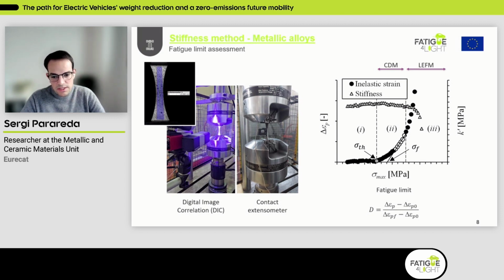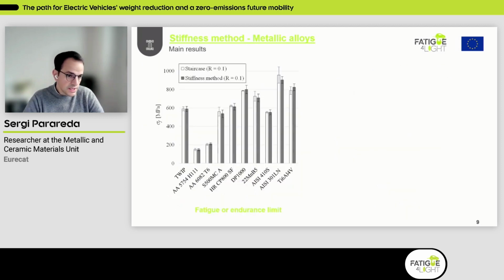And in the end, what we obtain is this graph that you can see here on the right-hand side, where we have the plastic strain plotted against the applied maximum stress in each one of these fatigue blocks. And we can identify different regimes, mainly related to the fatigue damage that we saw in the previous slides, and also to continuum damage mechanics and elastic fracture mechanics. We can obtain the fatigue threshold, so the point where something happens in the material, and then also we can define the fatigue limit of the material. So we can obtain extra data and compare it to the conventional fatigue tests.